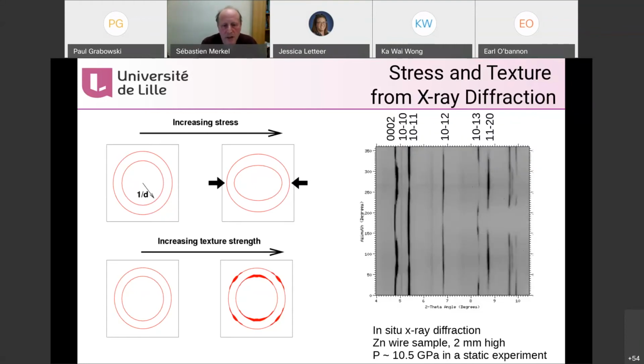And this is the same diffraction pattern plotted with 2 theta in horizontal and the azimuthal angle here. So you are turning around the diffraction rings when you move up. Sorry, I was pointing on the wrong screen. When you move up on the vertical direction, you see variation of diffraction intensities with orientation, that is texture. You see variations of peak positions with orientation, which is strain, and from which you can try to invert stresses. So it's very commonly used in static experiments. The idea is to do that on the shock.